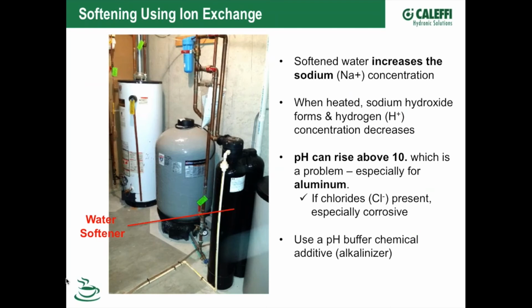Okay. Well, the second choice was water softening, which uses typically ion exchange technology. Basically, the resin is a positively charged resin that removes positively charged minerals in solution, with sodium on the beads, specifically calcium and magnesium, those that contribute to lime scaling. But what happens is that as the magnesium and calcium gets captured, and to a very small degree iron, they get captured, but in exchange, the sodium gets kicked off and ends up going into your water. So the sodium content increases inside your water.